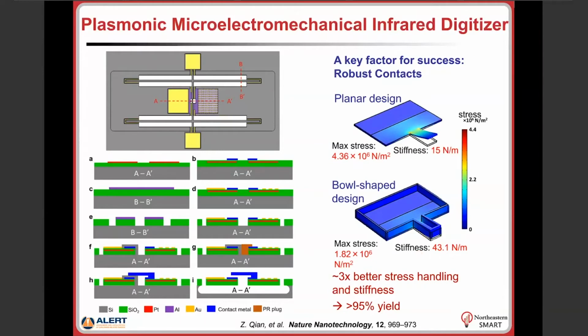By using this bowl design shape, we can get about 3x better stress handling and stiffness compared to what we would get with a planar tip design using the same thickness of the metal layer. And we can achieve this interesting tip design with more than 95% yield. That's something I wanted to highlight, because you will see that later on in some of the devices that I'm going to show you.